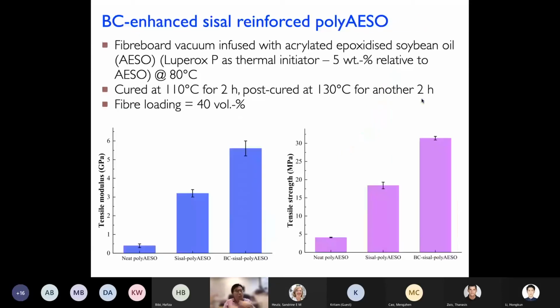We can actually take that preform that you have seen before. You can infuse that, again, with soybean oil. In this case, we were using Luperox P as the initiator. We polymerize it at 110 degrees Celsius. We post-cured it at 130 degrees Celsius.